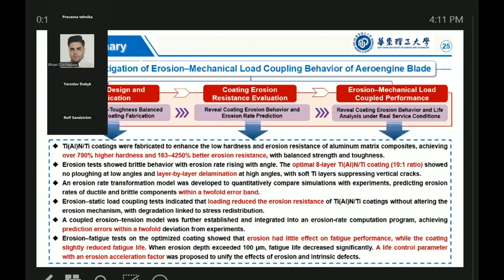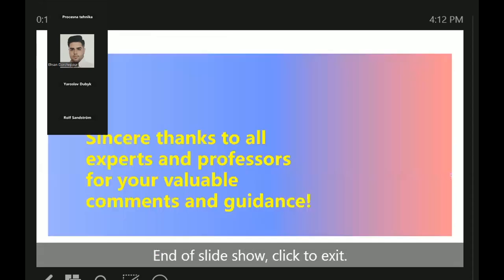And in conclusion, this study established a comprehensive framework for erosion and mechanical load coupling. We developed strong and tough multilayer coatings, revealed their erosion mechanisms, achieved accurate erosion predictions, and analyzed their behavior under realistic coupling conditions. These results provide an effective approach to enhance and evaluate the service life of compressor blades.